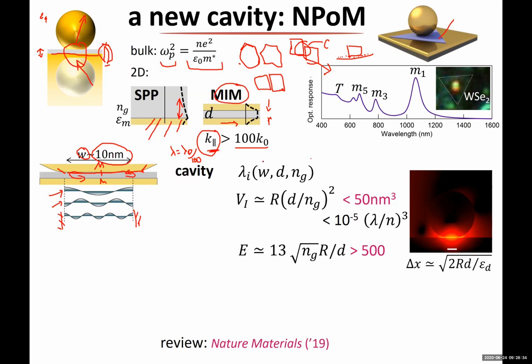So what's nice is that you can actually write down an analytical expression for the wavelengths of these different modes here, because it's basically a Fabry-Perot cavity. And then you can derive things like the volume of the cavity. So it just depends on the radius of the nanoparticle and the size of the gap and the refractive index. So we find that the volumes are indeed below about 50 nanometers cubed, 10 to the minus 5 of the wavelength inside that refractive index material. And you can also calculate what the field enhancement is. This is E over the optical field that you're exciting the nanoparticle with.